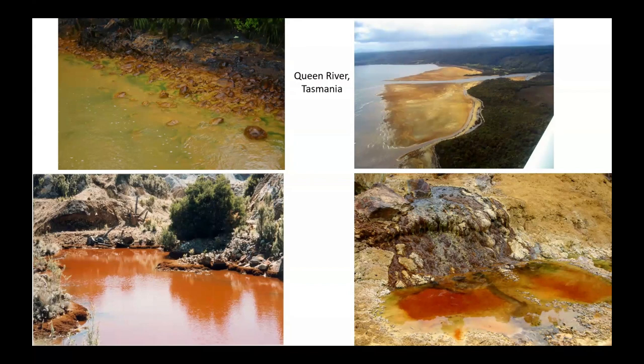Down the bottom, we see typical colours of acid drainage around mine sites, which can be, as I was just discussing with Richard before, surprisingly beautiful. The most beautiful site I ever saw was in the US, actually, which was a stream draining a coal mine site. In spring, it was going through a deciduous forest. The dogwoods were in bloom. The stream was crystal clear and the bed of the stream was brilliant yellow. And it was absolutely stunningly beautiful. But of course, the stream was completely dead. There was nothing living in it at all. So the beauty has a dark side.